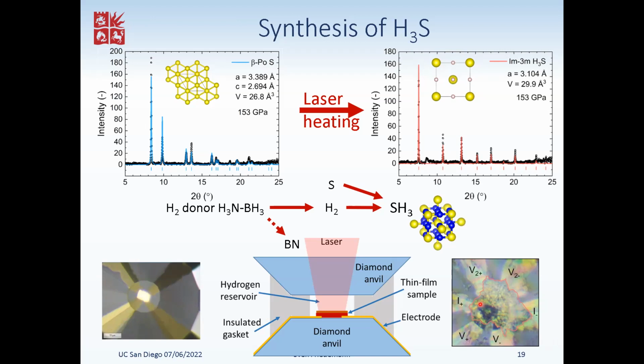We've done laser heating in one area only, which has now turned black here, whereas the rest of the sample is still, in this photograph, of gold metallic appearance. Actually, I wouldn't say that it is necessarily gold colored, the sulfur. That might be because the lighting here was also not white light. But sorry, under pressure, sulfur becomes metallic and superconducting itself, right? Yes. Do you see this too? Yes, I'll show it.